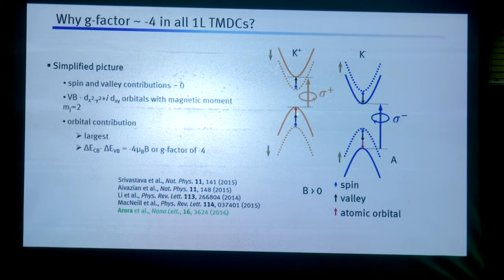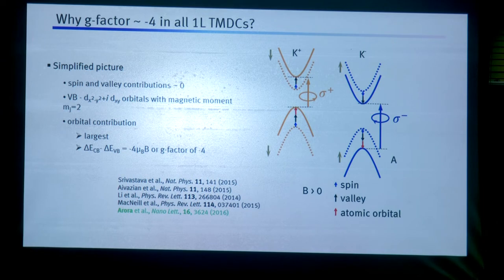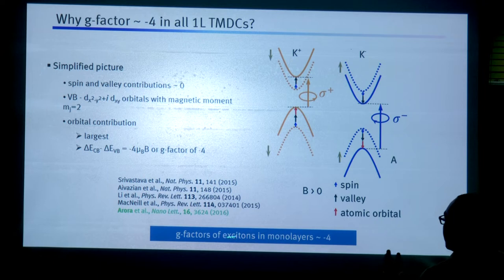The third thing is there at the top of the valence band, and that's the orbital magnetic moment, because the top of the valence band is made up of d orbitals, which has a magnetic moment of either +2 or -2. So this takes it up by +2, this takes it down by -2, so 2 + 2 = 4. This is the simplest thing, that these are the d orbitals which lead to a g factor of -4. Okay. So g factors of excitons in all monolayers which we have studied in 5 materials of this category are all -4.